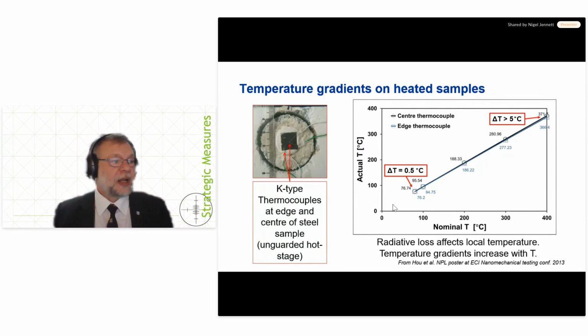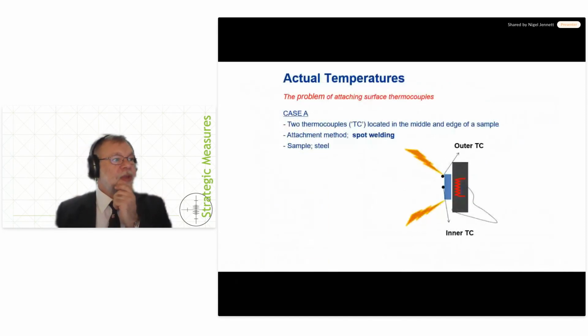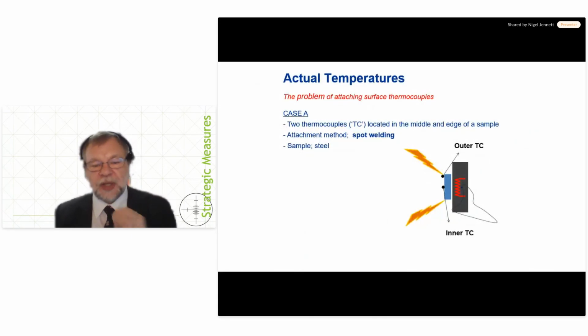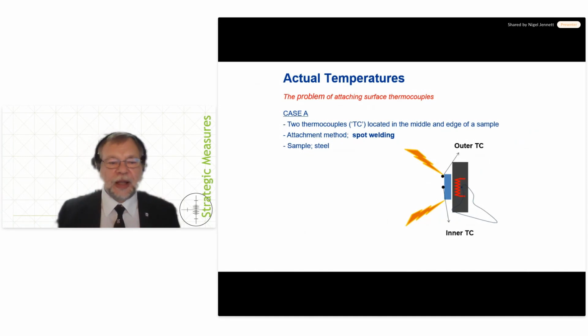And you can see this quite clearly if you put two thermocouples on a piece of steel, which is a pretty good thermal conductor. You can see that at around 100 degrees, you get a fraction of a degree, and it goes up to 5 degrees at 400 degrees Celsius. And that's just over a centimeter or so of steel on a hot thing. And people sort of think, oh, okay, 5 degrees, maybe that's not so bad. But the issue is, how do you actually attach the thermocouple? So if you've got a piece of steel, then the temptation is, well, just spot weld it. That's what we would do. And then you get a very intimate thermal contact, and that's quite a good idea.